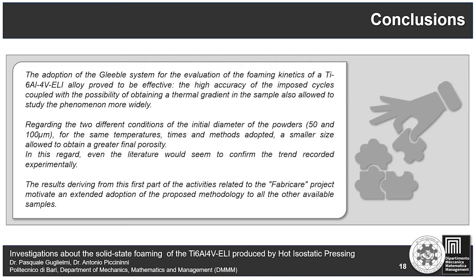In particular, the high precision of the imposed cycle and the presence of a thermal gradient in the sample made it possible to study the phenomenon extensively. As regards the two different conditions of the material, considering the same temperature, time, and method adopted, a smaller size of the titanium powder allowed us to obtain a greater final porosity. Even the literature seems to confirm the trend experimentally recorded.